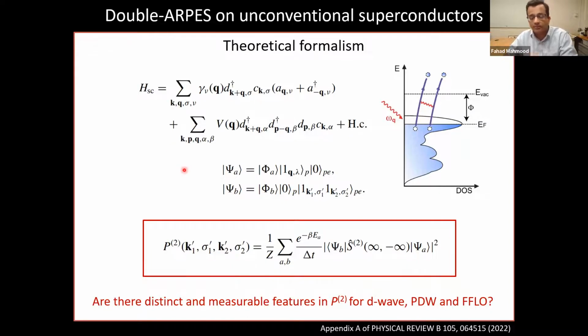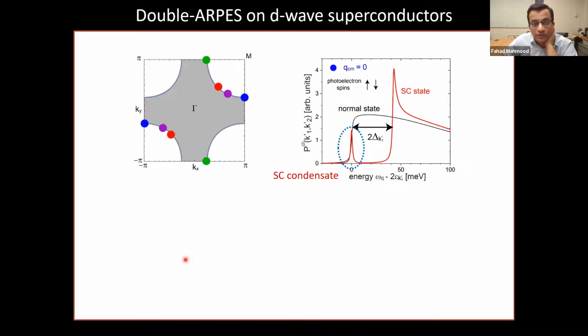So using this and then putting in different symmetries for the superconducting order parameter, we can calculate what this should look like, all right? So if I do this on just a regular D-wave superconductor where we have zero momentum, the Cooper pair momentum is effectively zero. So if we look at this two-particle counting rate between opposite points of the Fermi surface, we measure this peak here, the zero energy peak. And this is directly representative of the superconducting condensate, okay?